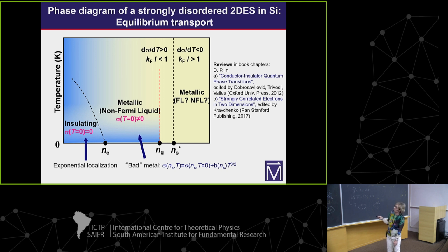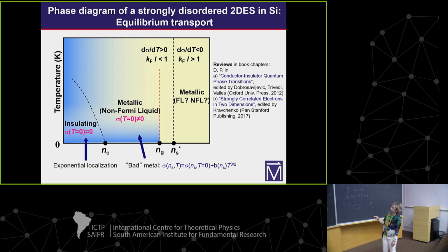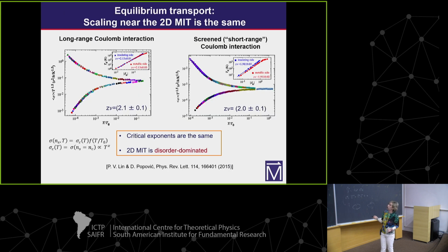So basically what we find is this metal insulator transition at some critical density, which is basically the same in these two types of devices, and then we have this some kind of bad metal regime. The behavior seems the same, not affected by the range of the Coulomb interaction.